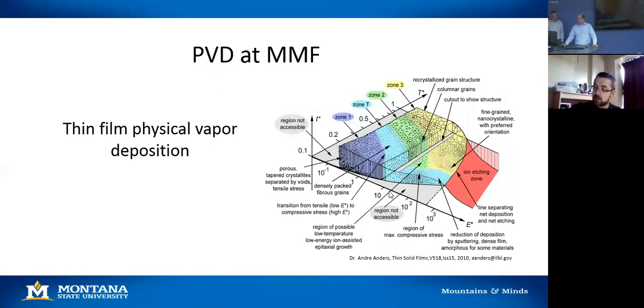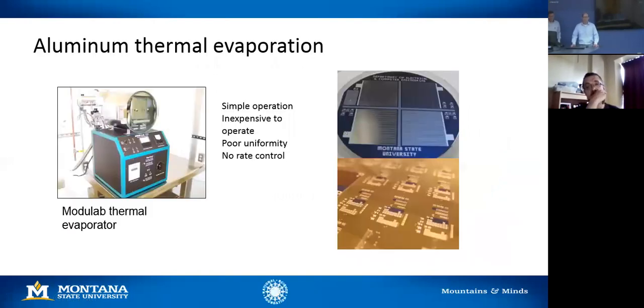Recently, with the addition of ion-assisted deposition and high impulse magnetron sputtering, now you have ion impacts with this deposited film, and so you can get densification of films. You can actually go into etch regions of the film. So with different tools and different capabilities in your tools, you have a broader area of crystal structures or polycrystalline structures you can get with these films. So these are not like a bulk grown film at all. Your properties depend a lot on the process deposition parameters as much as the material itself.